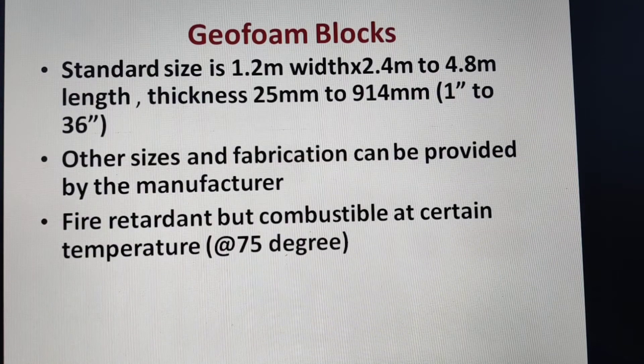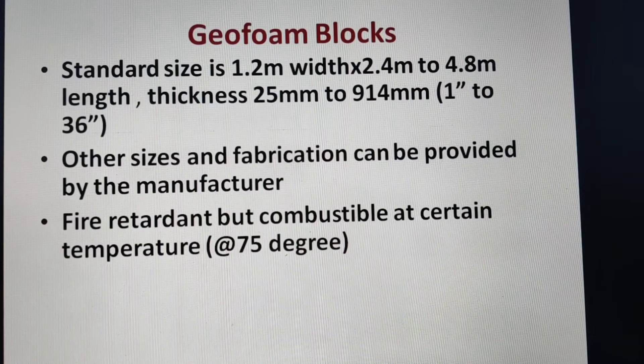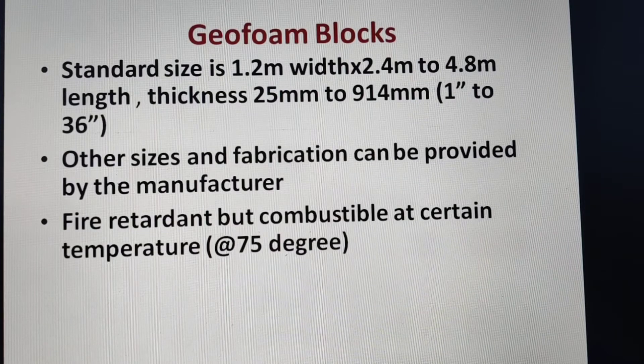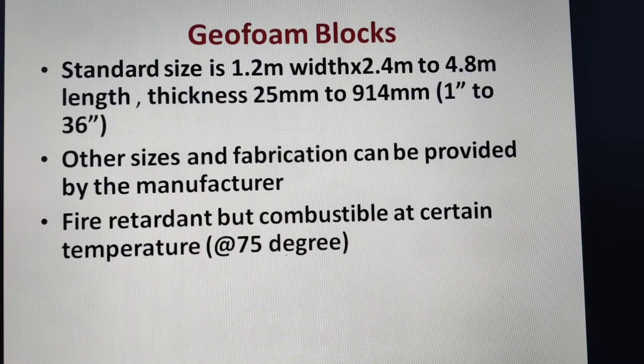They are available in standard sizes: 1.2 meters wide, with length varying from 2.4 to 4.8 meters. Thickness varies from 25 mm to 914 mm, which is 1 inch to 36 inches. Other sizes and fabricated shapes can be provided by the manufacturer.